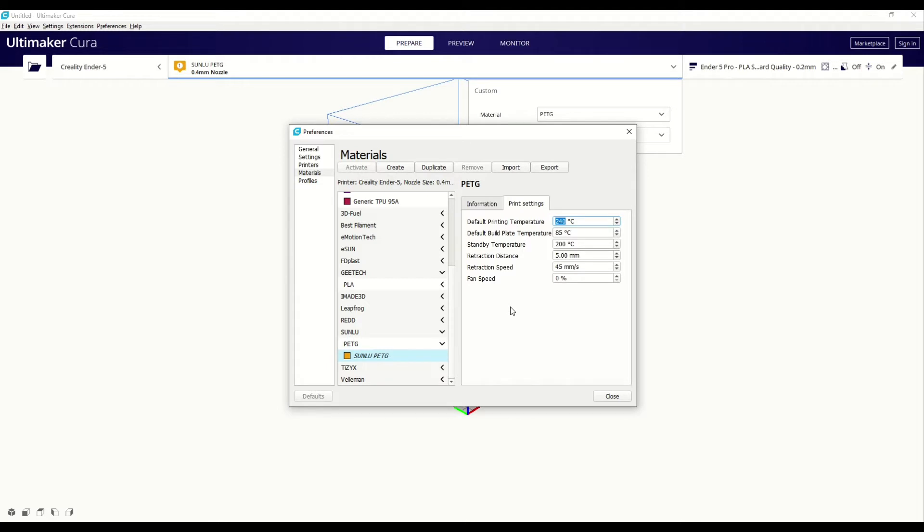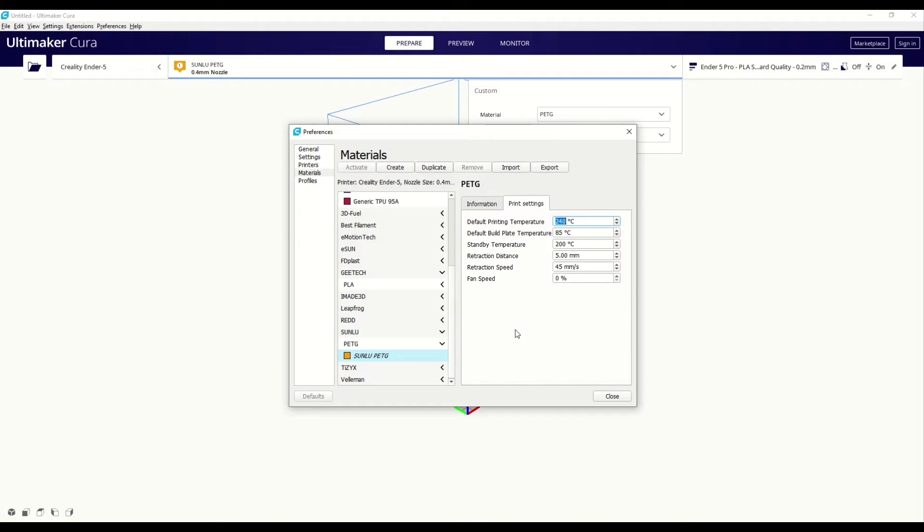I found that if I went any lower there were some noises like clicking coming from the extruder which I figured was the extruder not being able to push the filament through quick enough which I put down to two things really: the print speed as well as the actual temperature so that it wasn't able to melt the filament quick enough at the lower temperatures. So 240 seems to resolve that and I actually did that during the prints by just doing the settings whilst it was printing and just went up to a higher temperature and found that the clicking noise from the extruder finished, certainly on the outer layers. There were some other issues with the extruder that I'll cover just after we've gone through these settings.